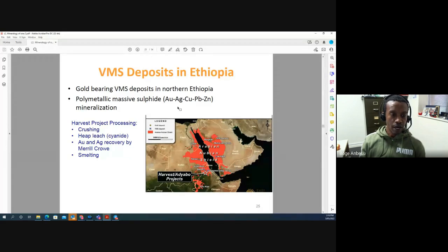Okay, so you mine, you float all the sulfides first, and then instead of leaching the whole material, which I think is what's happening from what I read in the flow sheet, you could probably just first separate out the sulfides, which are going to host the gold and the silver, and get rid of the majority of the gangue beforehand. And then once you have the sulfide, you could even consider straight smelting for gold and silver, okay, which could have been a lot more straightforward. And if you did it that way, you probably would get a higher recovery.